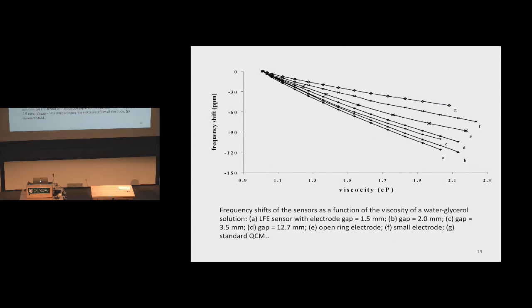And finally, we said, well, what about viscosity? This is one that surprised us a little bit. Viscosity is a mechanical property. And we figured that, well, the LFE probably is equal to QCM, but we didn't think it was going to be superior to it. Well, here are the results. What you see here is the standard QCM in G, right at the top. And then A through F correspond to the LFEs of different spacings and even the open ring and small ring geometries, which I gave figures on earlier. And you see that of all of those, again, the LFEs are grouped together, and this one right here, the A group, has the biggest shift.